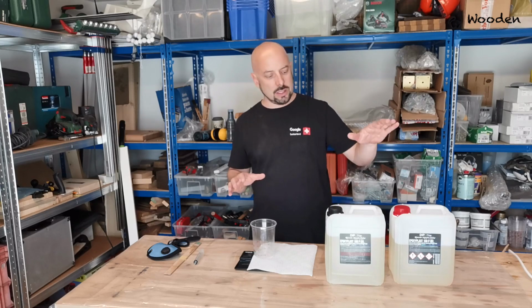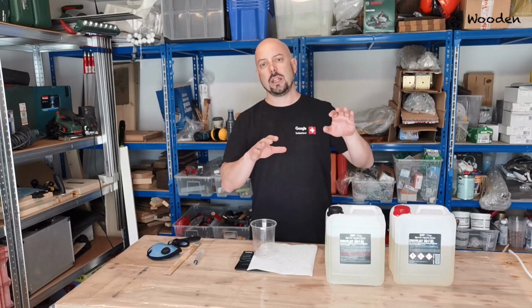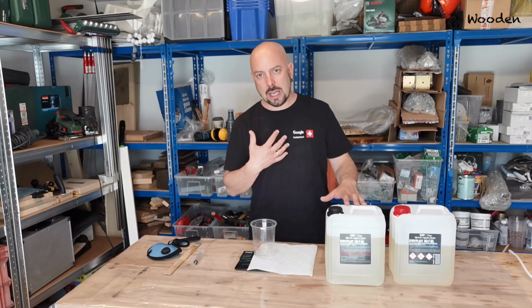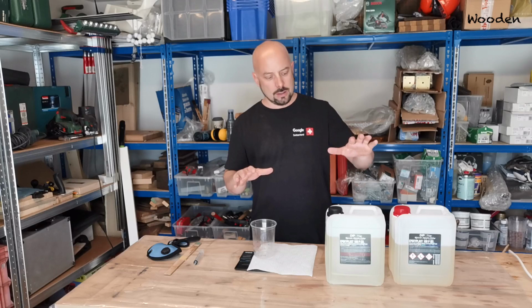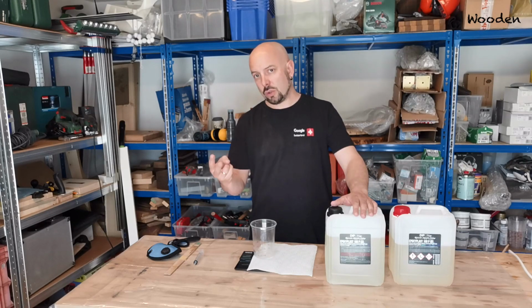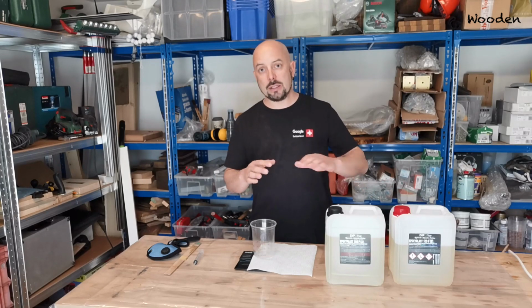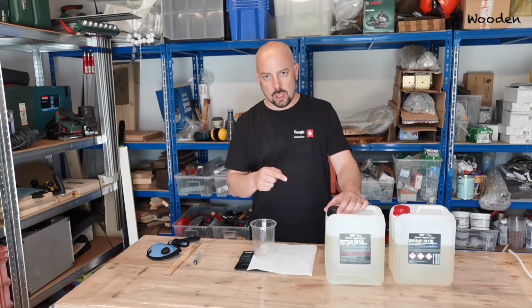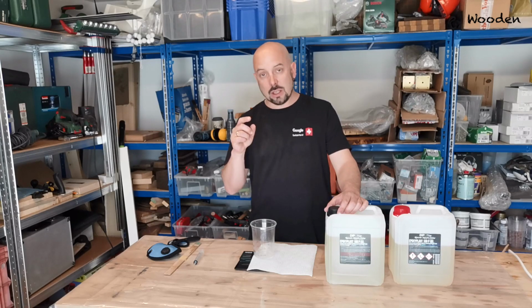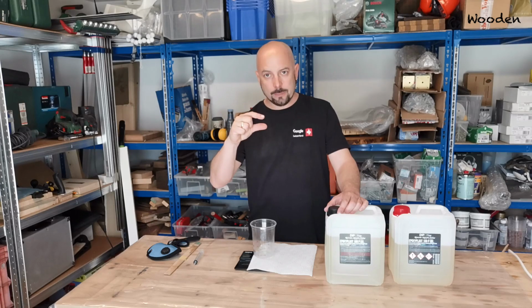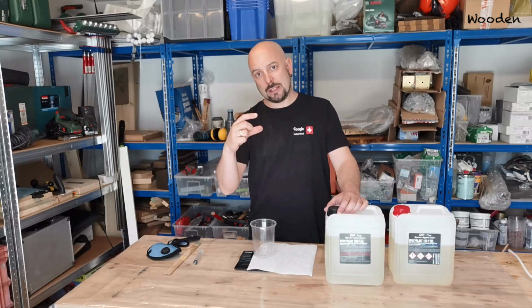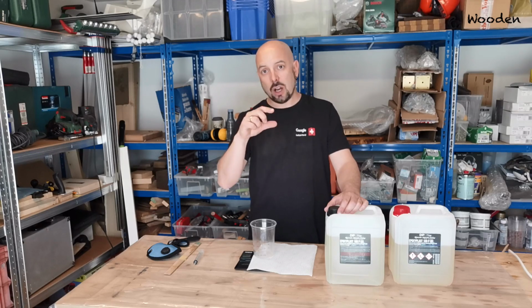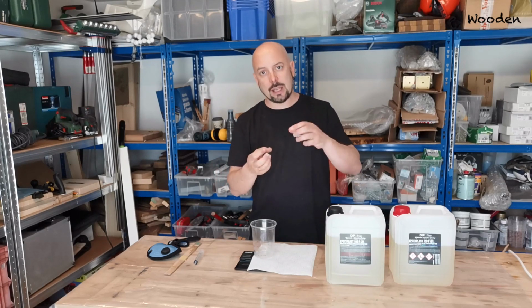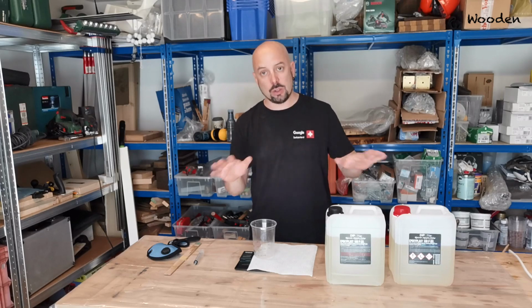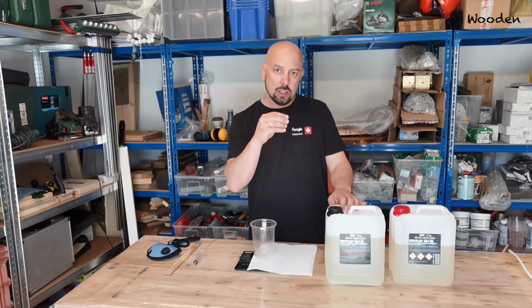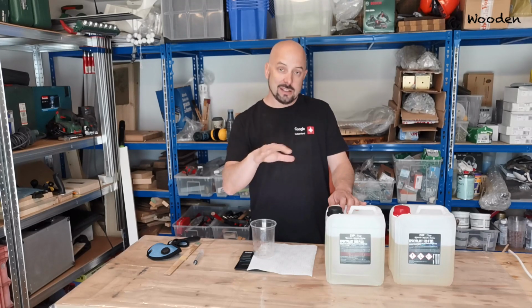When you buy epoxy resin, you need to look at your epoxy resin to see in what ratio you have to mix it. Most epoxy resins I know of are mixed like the component A is 2 units and then 1 unit of the hardener. But different epoxy resins have different ratios, so you have to look at your epoxy resin. You also need to look at it to see how thick you can pour it. The thicker you can pour it, the more expensive it is. And the cheaper epoxy resins, you cannot pour a lot of it because then it will overheat and it will break. And that happened to me too in the past, so you don't want any of that to happen. So you need to check your epoxy resin, how thick you can pour it, and then apply it like that.